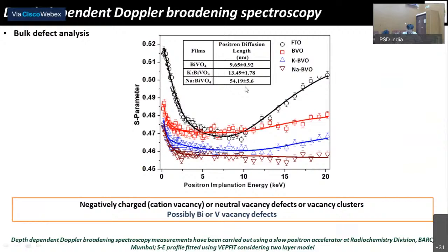That shows that with the doping of sodium, the defects are decreasing in the case of the sodium doped bismuth vanadate system, and that gives a positive result for the water splitting. That's why we see the enhancement in photocurrent density during the water splitting reaction.